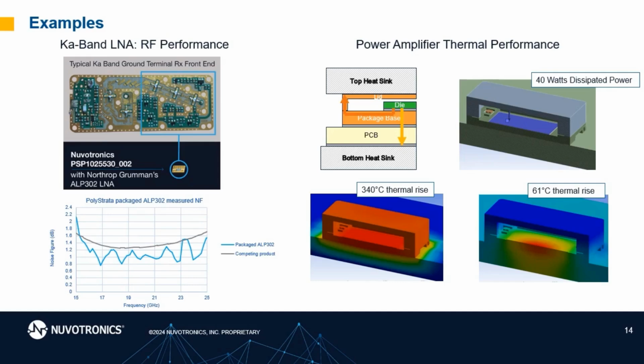The other application benefit is thermal performance. So the RF performance is shown on the left, and the thermal performance is shown on the right. In this example, we show 40 watts of dissipated energy through the backside of the die for a power amplifier. And at the bottom there, you see the comparison between the different heat paths. So on the left side is an absolutely not acceptable thermal rise of 340 degrees C.